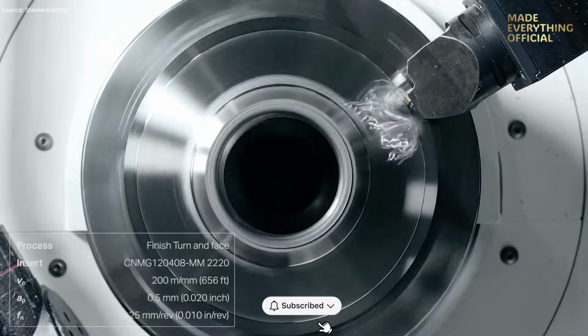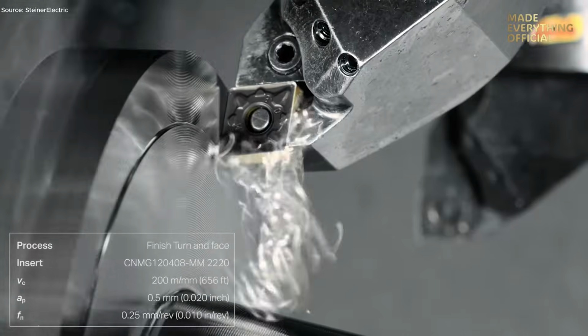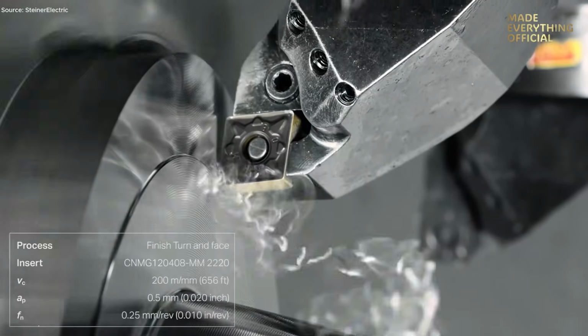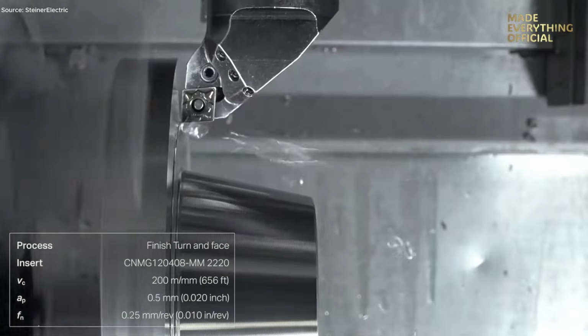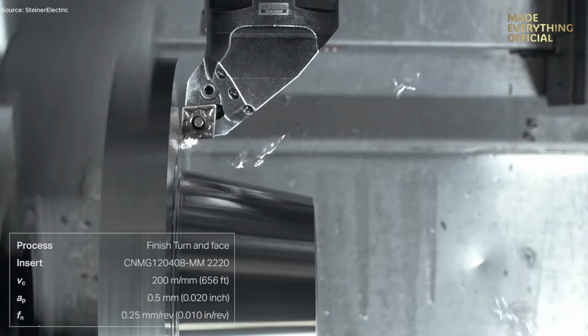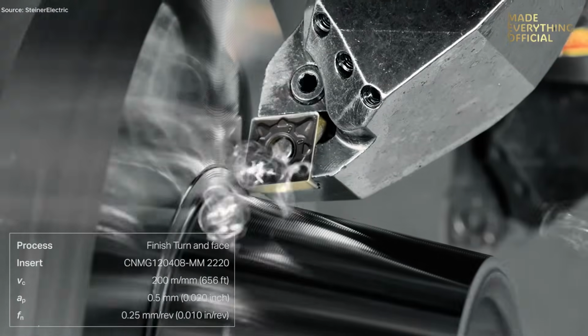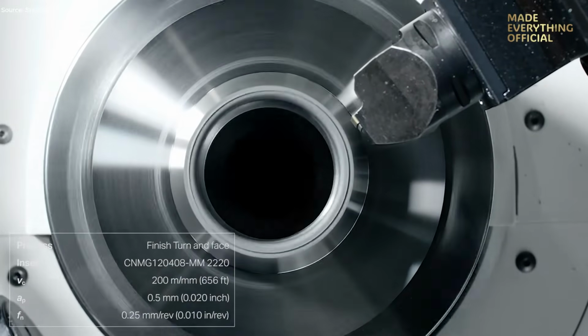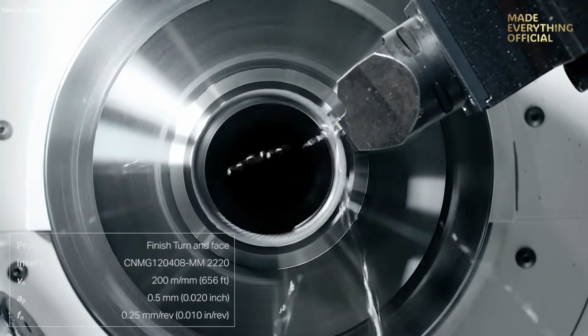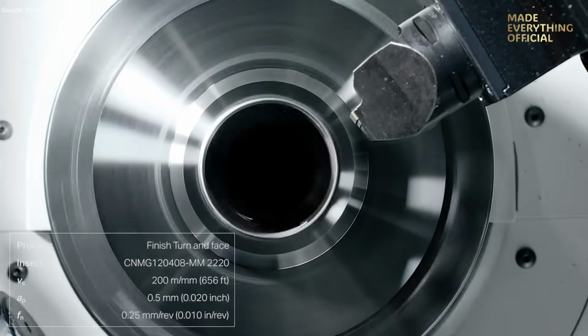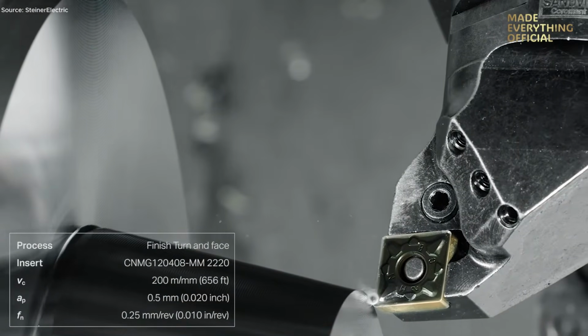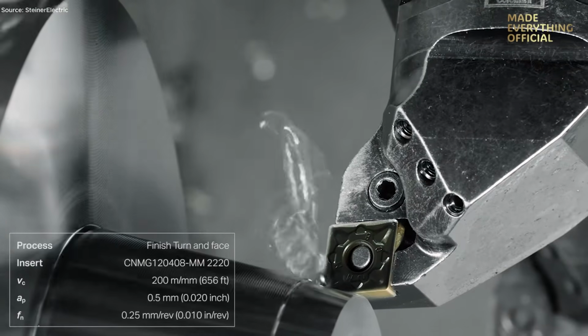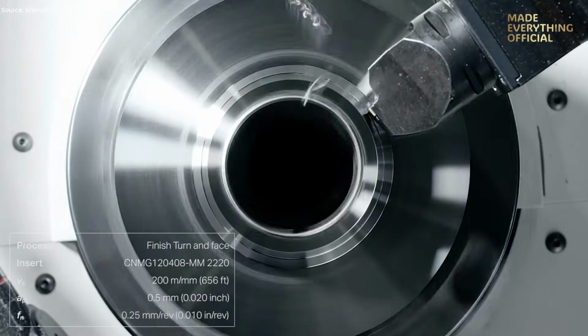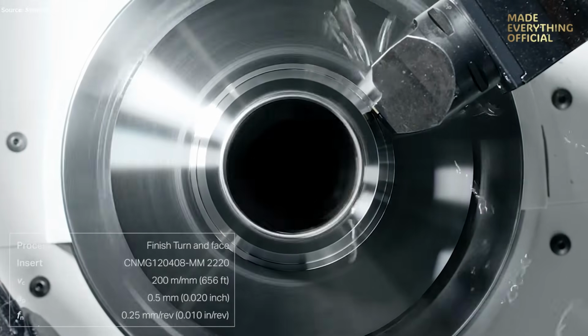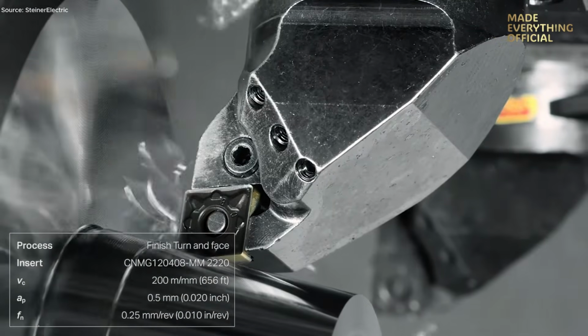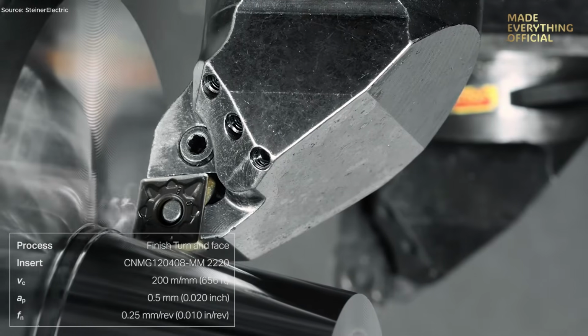Once the rough phase is complete, the tool transitions seamlessly to a CNMG 120408mm 2220 insert for fine turning. Here, precision takes over. The spindle accelerates to 200 meters per minute, and the depth of cut drops to just 0.5 millimeters, maintaining a feed rate of 0.25 millimeters per revolution. Every micron is controlled, every vibration dampened. The tool path flows with surgical rhythm, cutting smooth, reflective surfaces with near-zero deviation. Finally, the system prepares for the finishing bore, the stage where tolerance becomes perfection.